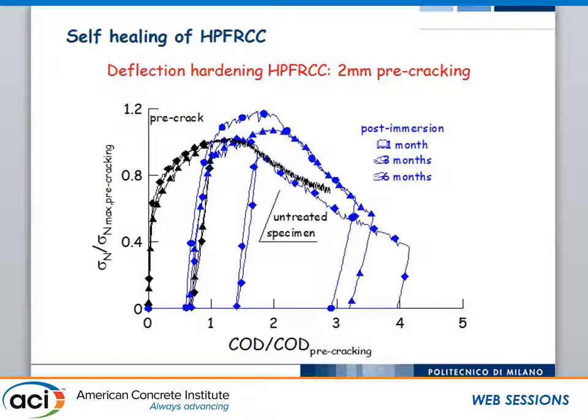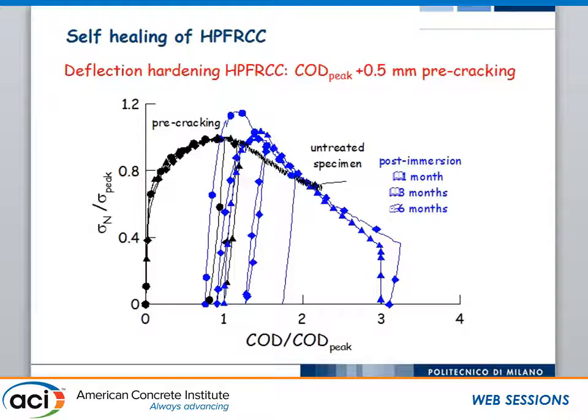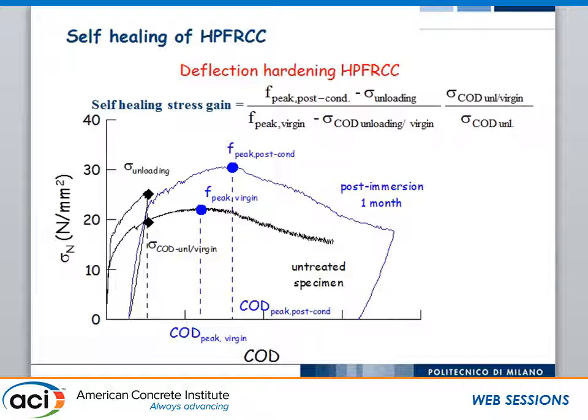And even in the case where the specimen was loaded after the peak, so we had a quite wide, single, open, localized crack, we had some capacity of the material to undergo some stress gain and some ductility gain after exposure in water. So we decided also in this case, this is a preliminary analysis, a preliminary reduction of the results, we decided to try to quantify this effect of self-healing, so just to see what kind of strength reserve, in a sense, we could have between the pre-cracking level and the peak level for the monotonically loaded specimen, and how does this change